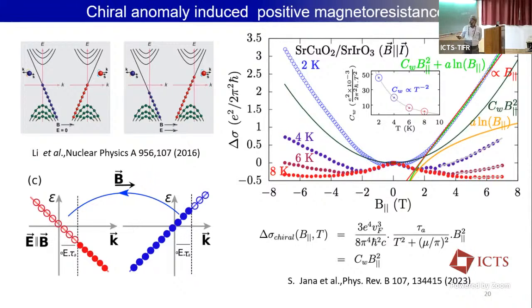Now you see this is the data where we try to fit it with this expression. This is coming from your chiral anomaly, and of course there is a term coming from the localization effect, and we see that the data matches well with this expression. If you look at the temperature dependence of this part, it varies as T to the power minus 2, which is expressed here as this C sub W. This tells us there is a contrasting difference between bare SrIrO3 and when you are sandwiching with an antiferromagnet, and this tells us that there is topological electron transport. But the point is why?